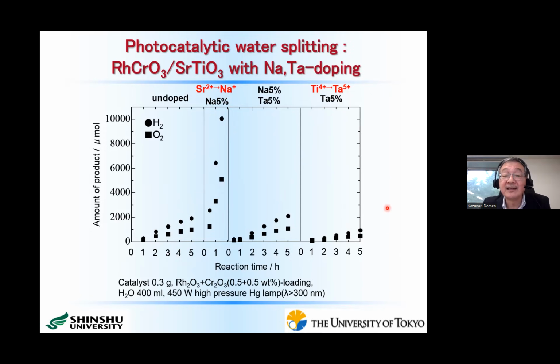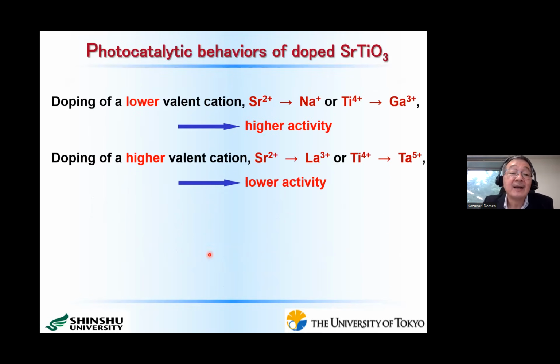This kind of tendency can be generalized like this. With doping of a lower valent cation, for example, A site strontium 2+ by sodium 1+, or B site titanium 4+ by gallium 3+, we can get higher activity for the overall water splitting reaction. On the other hand, with doping of a higher valent cation, for example, A site strontium 2+ by lanthanum 3+, or B site Ti 4+ by tantalum 5+, the activity of the water splitting reaction becomes lower.